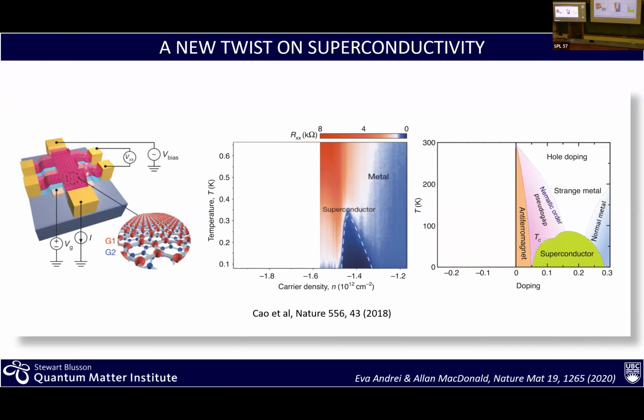And if you look at the graphene case, where you tune the electron density now by a bias voltage, not by, let's say, chemistry, you can see superconductivity, you can see more conventional metallic behavior. And here in the middle, in red, you see an insulator, a correlated insulator. Now, what is interesting here is that these are phase diagrams on what we call the hole-doped side of a phase diagram. We put holes into it, but we can also dope an insulating cuprate with electrons and go into the other side.